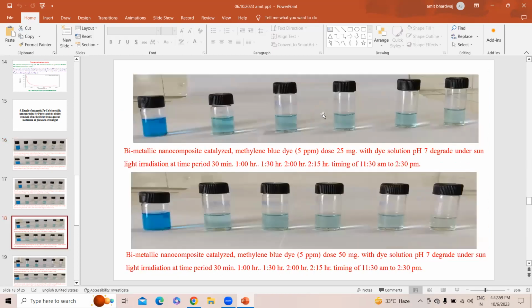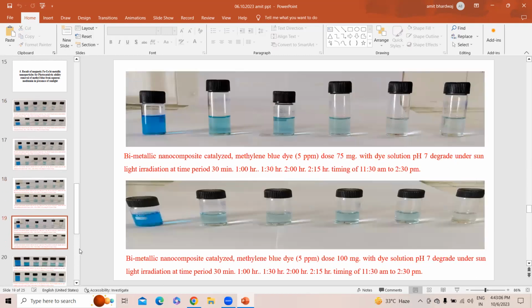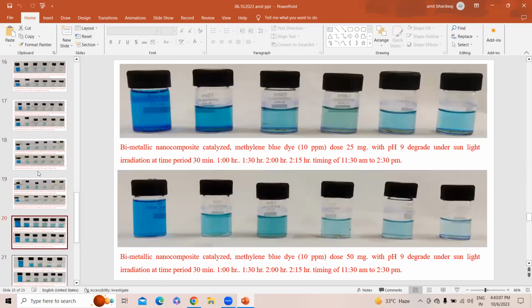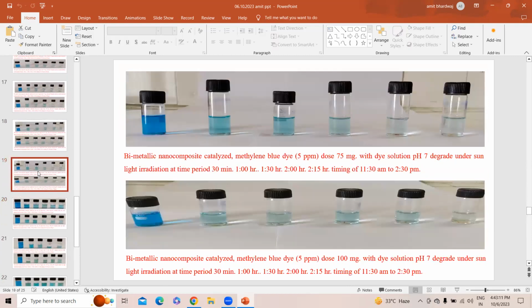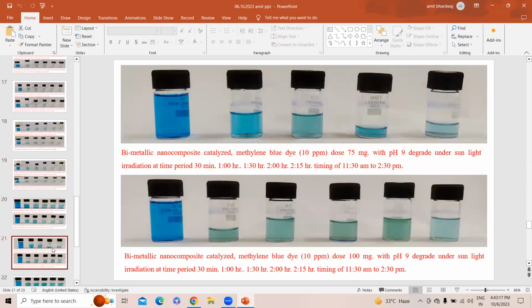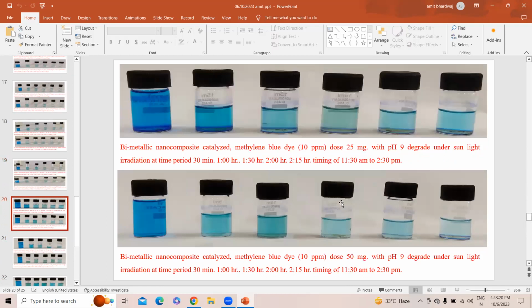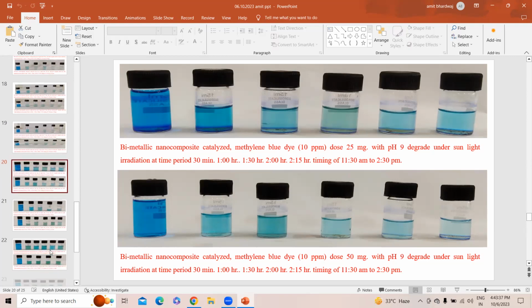Again, we change the pH, with the dye concentration fixed and the dose changed to 25, 50, 75, and 100. Again, we prepared methylene blue dye solutions of 10 ppm, and the dose changes of 25, 50 and so on, with the same pH and same concentration of dye, but different doses. We can see the color of the samples change, because this color change shows the degradation of dye at different doses.